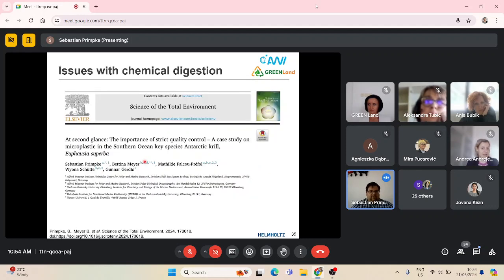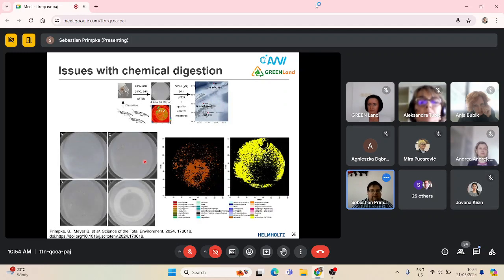The second thing we just published a few months ago was an investigation of krill samples from Antarctica. We wanted as few digestion steps as possible because we were aiming to analyze the stomachs. So they were dissected from the samples, put into KOH, and directly put onto an analytic filter after we neutralized the solution. It was a rather simple setup, and then we ended up with